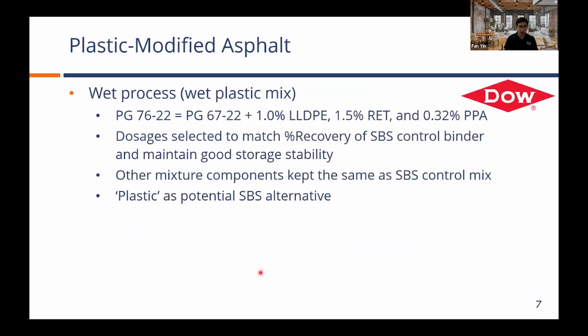One thing I would like to clarify is that even though we call it the wet process of adding recycled plastics, the formulation that we use in the test section of the test track is really not just about the plastic. And there are good reasons for doing that. For those of you who know, asphalt binder and plastic do not like each other. We can use high temperature, high shear, low shear to force them together, but once you stop that agitation or the temperature history, those materials are going to separate.